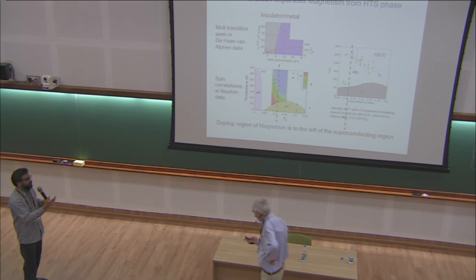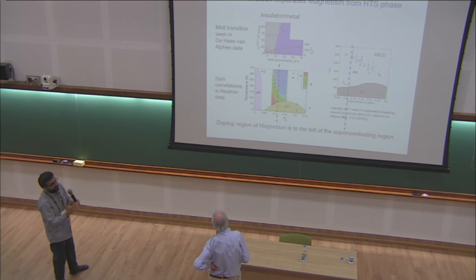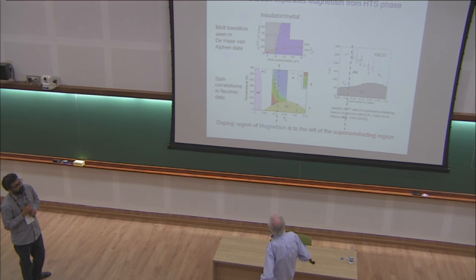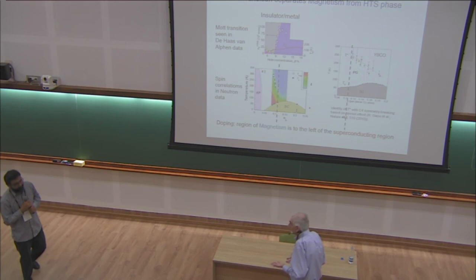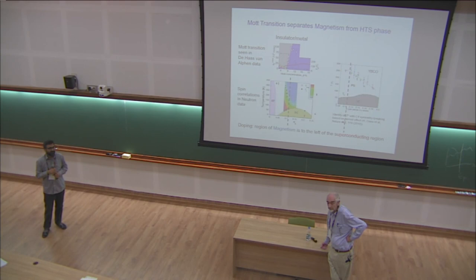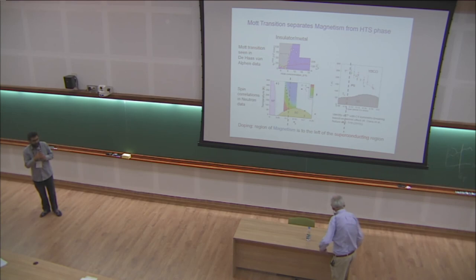One view of high-TC is that the normal phase itself is pretty puzzling. The place where you show the isotope effect to have the least effect, you would see in the experiment that the normal state is very anomalous. It has no quasi-particle, it's very non-Fermi liquid. Where is that captured in your theory? Well, that's at 15%. I agree the 15%, this dashed line which is a Mott transition. Here, if you look at the Fermi velocity, it's very much higher than here. So it's sort of like a glass half full, glass half empty. Obviously there are a lot of residual correlations. Even though there are only a few percent changes in this doping, there are huge changes in the nature of the systems. We are really well away from the Mott transition at 15 percent, I would say. But have you looked at the spectral function of the electron at high temperatures above your TC at, say, 0.15? I'm not too sure about that data. If you give me a reference, I'll look it up and we can talk about it at the meeting. To anybody who wants to continue their questions, I'm here for the week, and I'd really appreciate the chance to learn more about more data or more theory. Let's thank Dr. Noons again.